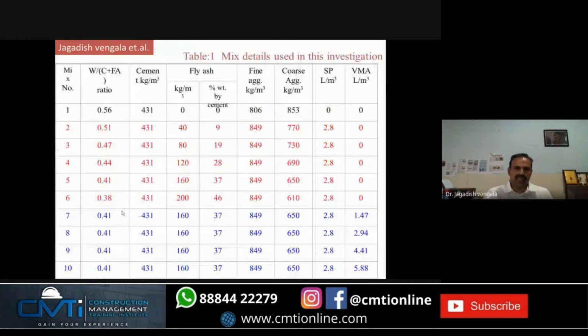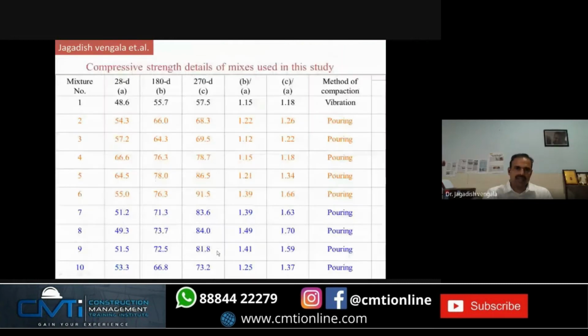You can see here for a replacement of 37% of fly ash, you can see the normal concrete to the 270 days normal concrete. There is an increase in 90 MPa. You can see here. What is that? 90 MPa. If 55 is your 28 days, 90 MPa is 270 days. That's the contribution, long-term contribution of fly ash, long-term strength concrete.